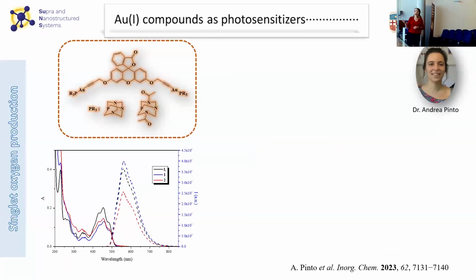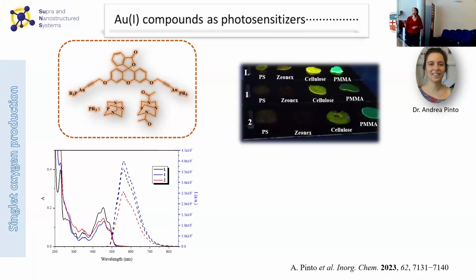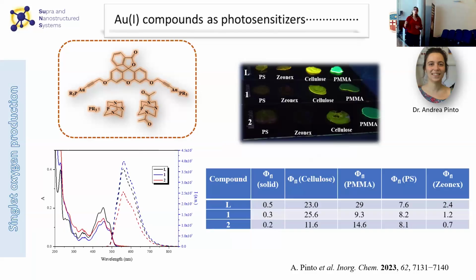So then Andrea synthesized this fluorescein molecule with 2 gold phosphine units. She characterized the emission properties in solution, but also in different materials. In these cases, apart from Zeonex and PMMA, we went to polystyrene and cellulose. And first of all, from the photophysical point of view, we can observe that when our samples are in these matrices, they display an emission quantum yield that is much more favored than in the powder, let's say, in the solid state. So we are winning something, at least from the photophysical point of view.